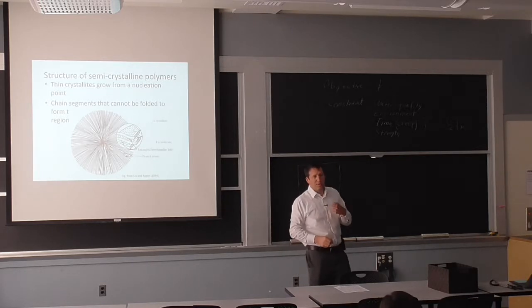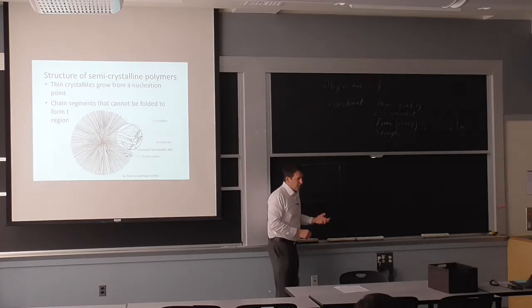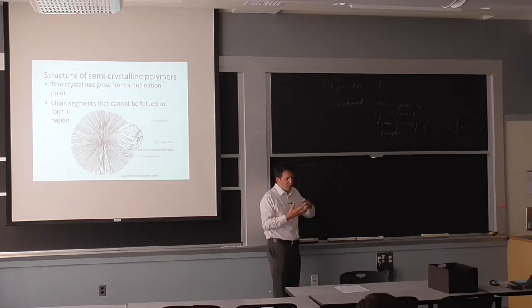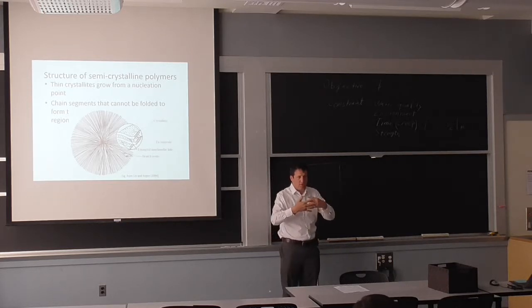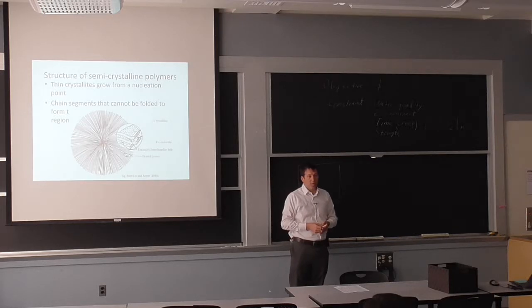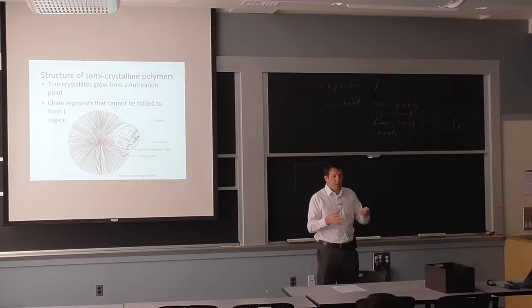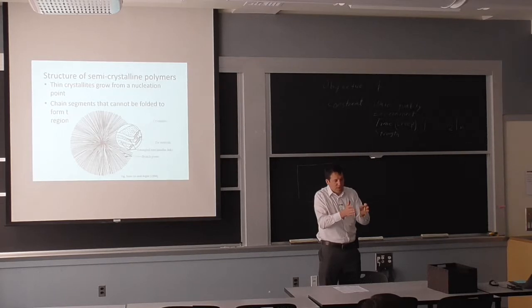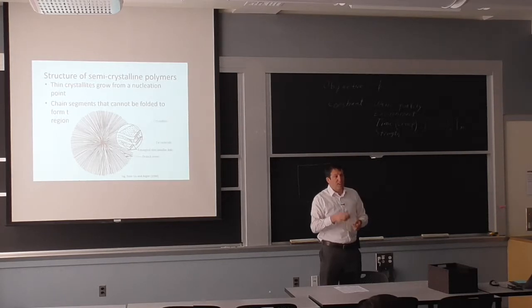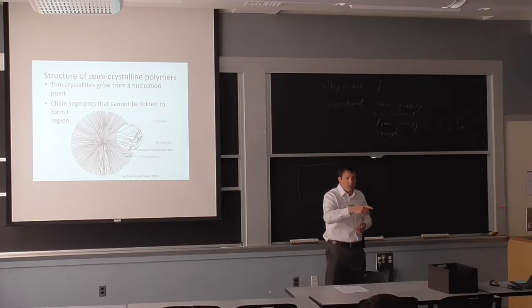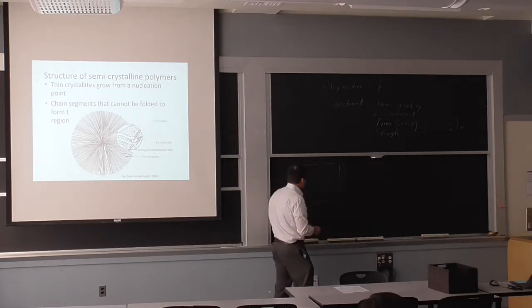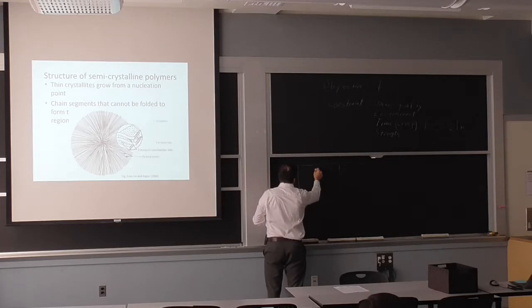crystallization temperature, which is very interesting, because of all this organization, there's a need for so much movement of the chains to get together that it will crystallize at different temperature depending on how much time you allow for that crystallization to take place. So if you think of just diffusion for metals, you have the liquid and all you need is to stack individual atoms. Here you have to stack actual long chains of molecules that have all these side groups. So it's a very slow process. Say it happens at a few locations inside, it will grow from there, and that's what you see here.